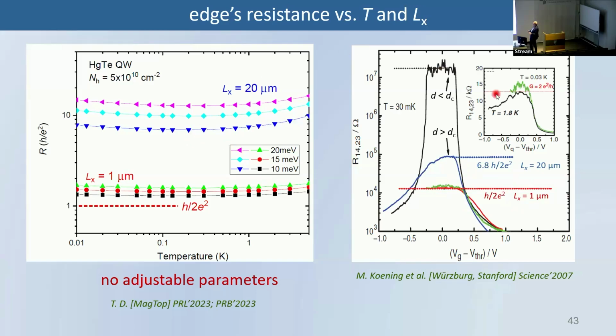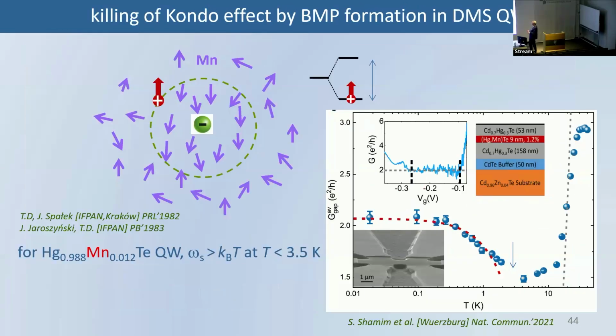But if you take a larger value, as here, you get much larger resistance, because backscattering occurs, and the transmission coefficient for this one-dimensional transport is not 1, because electrons scatter back, and this reduces current and gives higher resistance. So this is the kind of understanding of quantum spin Hall effect, that due to proximity of these helical states and presence of impurities, there is no topological protection, or very weak topological protection.